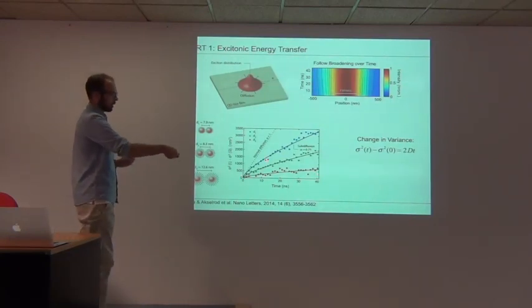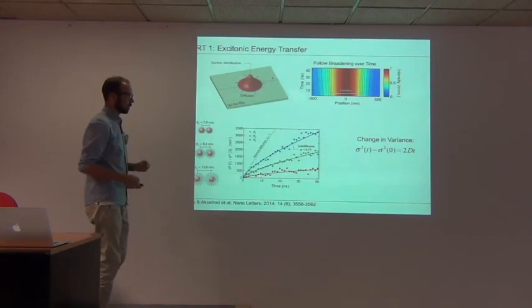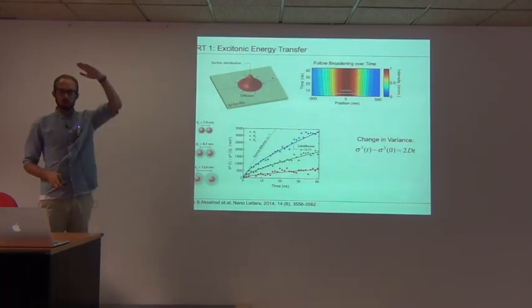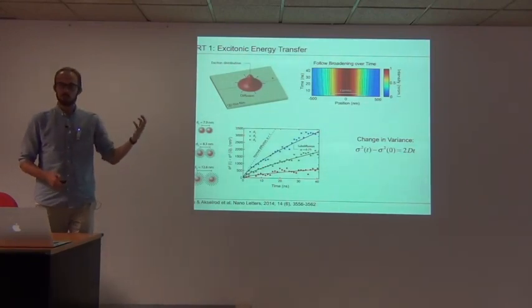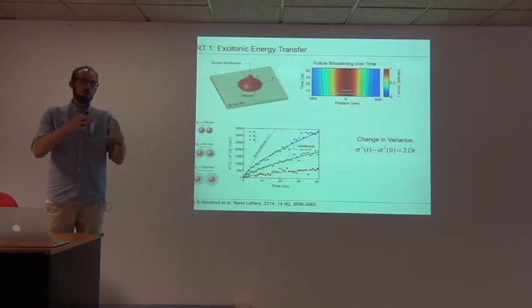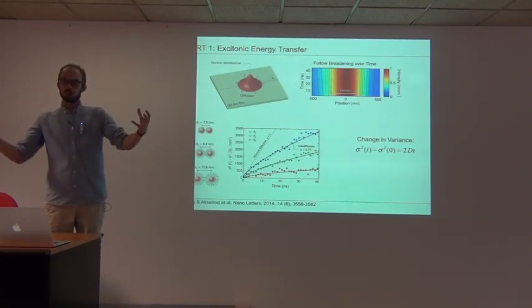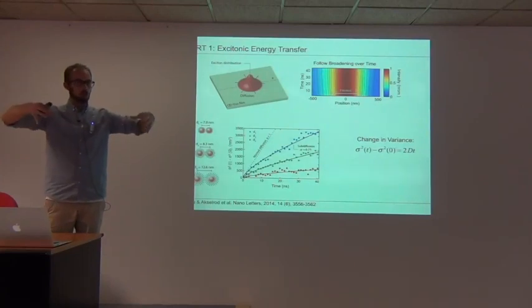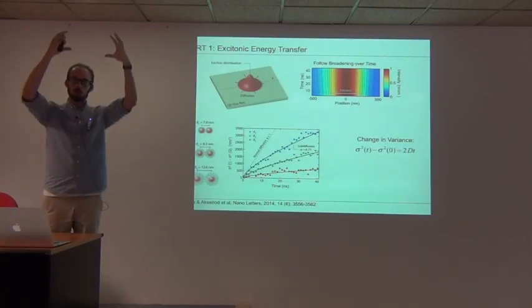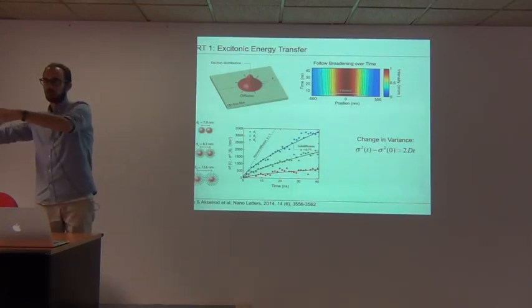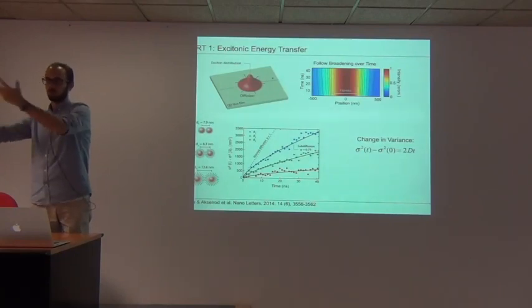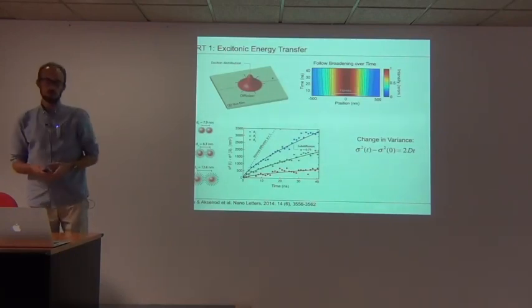What was a little bit less expected, or more dramatic than what we expected, is that it slows down as time goes by, and this is a clear indication of energetic disorder. So if you have high energy sites and lower energy sites in your system, in the beginning you probe all of them, but as time goes by you are populating more and more of the low energy sites, which have more difficulty giving off their exciton to the next part.